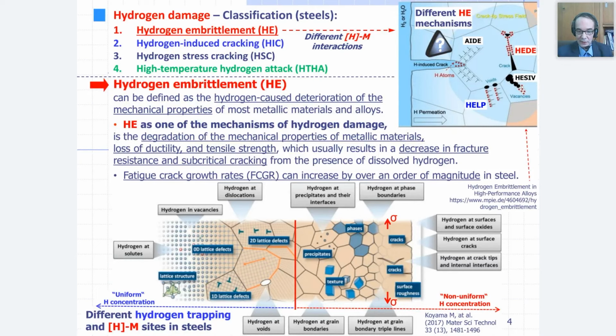As you can see on the down middle part of the slide, we have different locations for hydrogen trapping and hydrogen material interaction sites in steels. On the left side, we have hydrogen at solute. Hydrogen is in different defects of the lattice of our material, in 1D defects and 2D defects, like in vacancies, in pre-existing voids, or at dislocations.